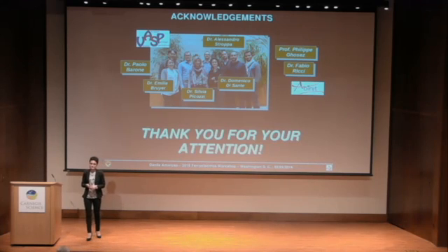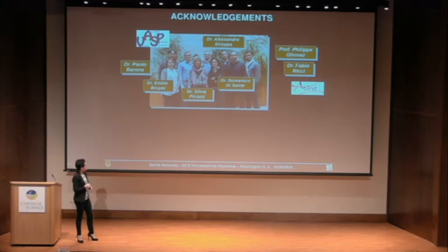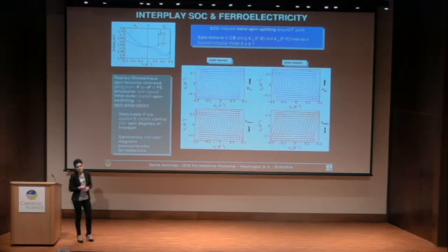Yeah, thanks. The Rashba splitting is in your conduction band, right? So that's empty states. Now, if you want to use that in spintronics, obviously you're going to have to populate them, which means pulling these states down below the Fermi level, presumably by doping or something. But then if you do that, you've got density of states at the Fermi level, and will the ferroelectric state be stable, or will it be destabilized?